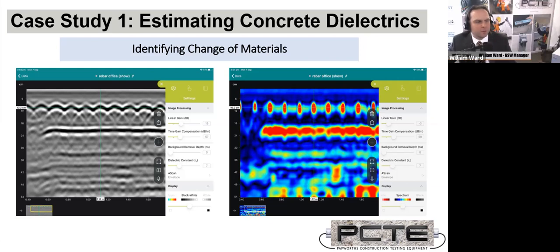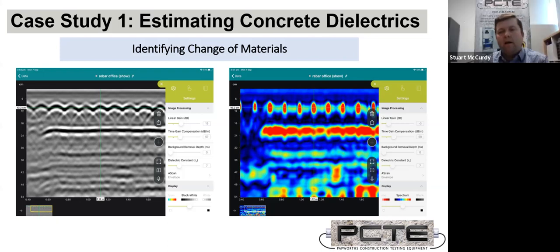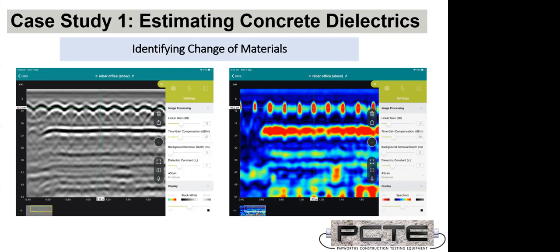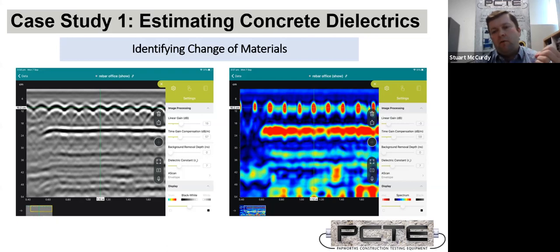Just a quick question from Neil about whether a bond deck or metal decking would affect the reflection of the bottom of the slab, Stu. Yeah. So steel actually reflects all the GPR signal back, but because the rebar is small, we are actually seeing around the rebar when we see multiple layers. However, if you had a Bondek slab or a metal plate, basically, when you hit the Bondek, it just reflects all the signal back. So you won't be able to see anything below the Bondek.